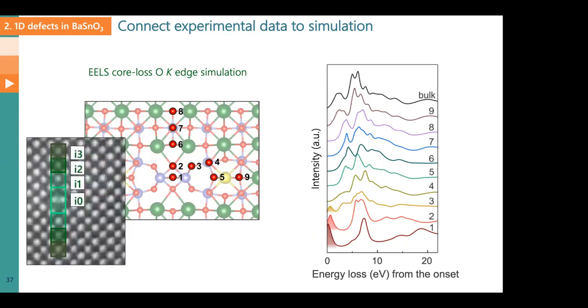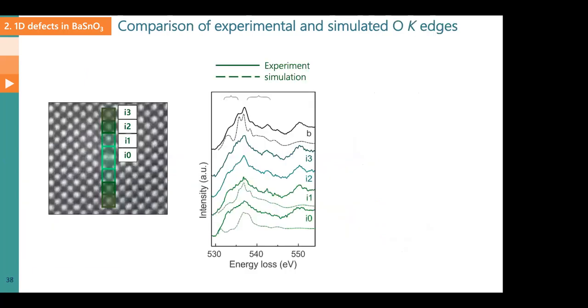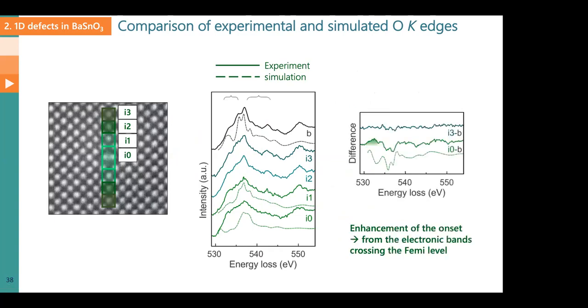And when we did a measurement, went to the structure and did a measurement, one unit cell at a time, one atom at a time, this is what we got. We got the reference, we got each location, and going up or down doesn't make a difference. It's all reproducible. We did it in many cases, and now we are comparing them. If I compare, for example, location 3, which is far away from the core of the defect, to the further away bulk performance of the material, basically the difference is noise.